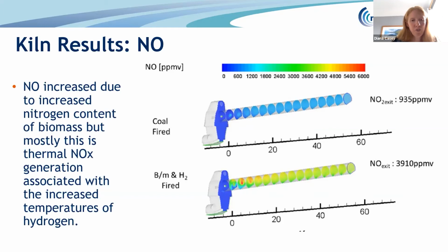Now, oxides of nitrogen, or NOx, are another interesting one, with significantly different results for the hydrogen and biomass case compared to coal. The use of biomass, which naturally contains significantly more nitrogen than coal, increases the production of NOx. The blue end of the scale is very low NOx production, whereas towards the red and yellow end, we're getting a lot more NOx. As well as the biomass, the higher temperature of the hydrogen generates thermal NOx too, so we've got this massive increase, and the diagrams look really different. So that's just a few of the results for the kiln.